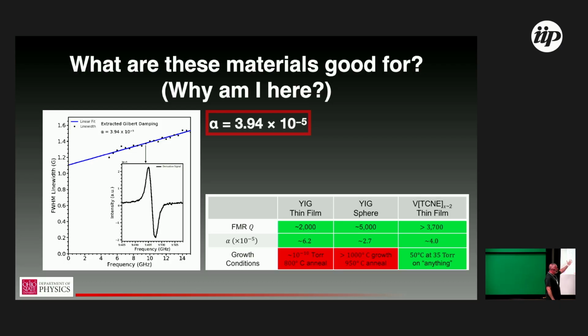And then pivoting now to why am I here in a quantum magnonics workshop, given that was a very materials intensive introduction. And you can see that here. So I mentioned earlier that the Prussian blue has a damping parameter of 10 to the minus 4. Good but not exceptional. V[TCNE]x films have mid 10 to the minus 5. YIG is the only other material that does this. This still astonishes me, honestly, in both directions. I mean, there's to date 2 materials ever discovered that have magnon damping this low.